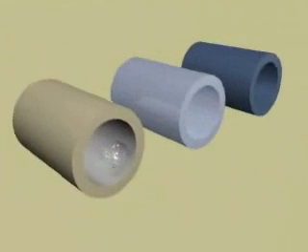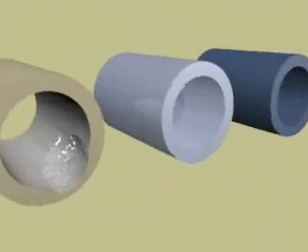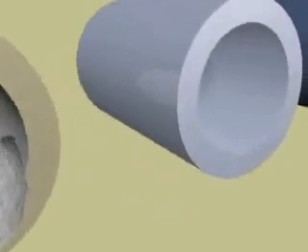The process provides full-volume coverage and is sensitive to metal loss down to 9% or more of the pipe wall section, whether it's caused by erosion, corrosion, or as we see here, in-service damage.